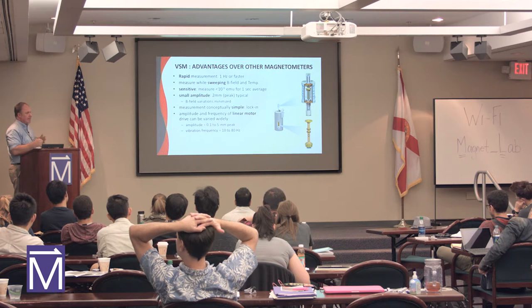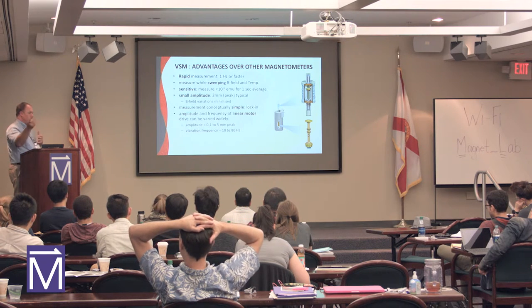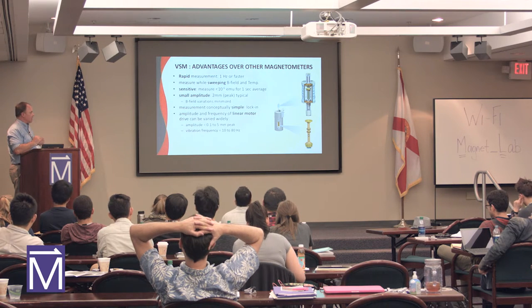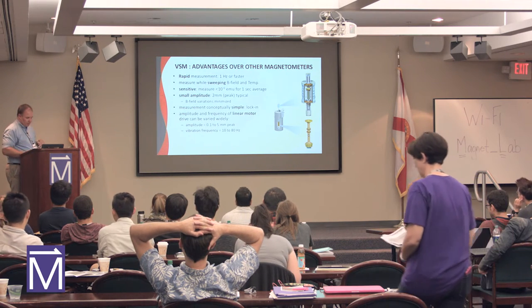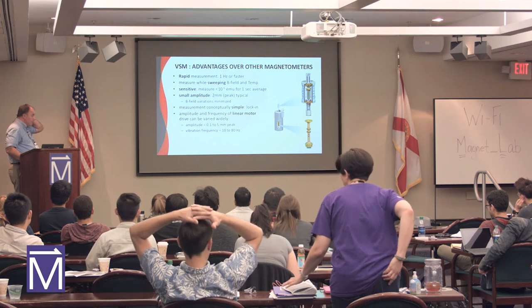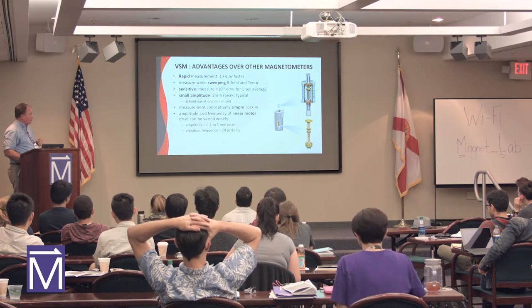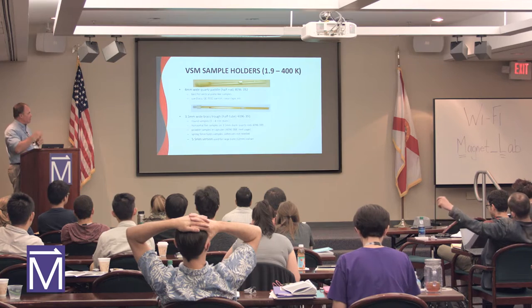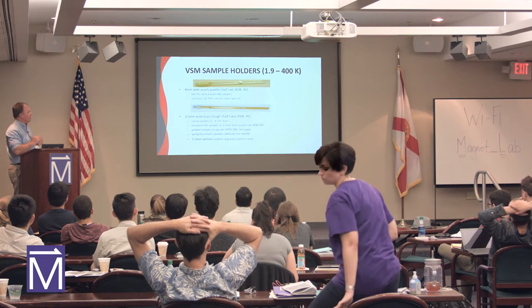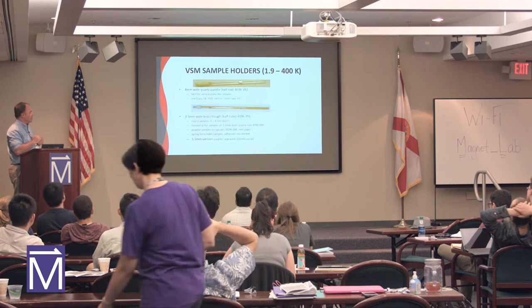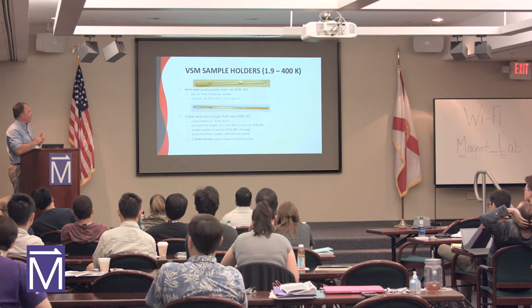VSM's a lock-in technique, so we take the motion as a reference signal, and we can demodulate that reference signal. You can drive the motor from 10 to 80 hertz. It's about a 10 millimeter plateau on the homogeneous region of the magnet.